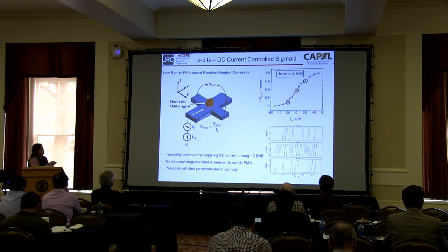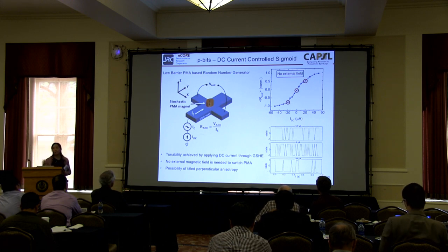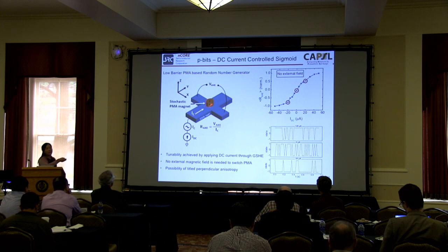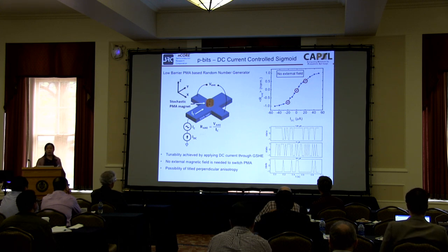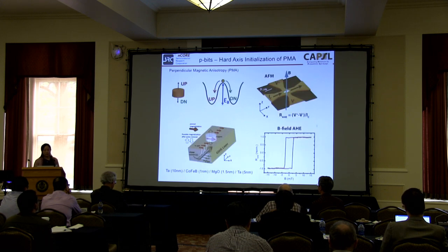And then now let's come to the device. I would like to really control this input through electrical means. So now we actually have our whole bar made out of a giant spin Hall effect material that actually offers spin-orbit torque. So I can really impact the magnetization of my magnet through the GSHE layer. And so here we apply a DC current. And again, you see the sigmoid curve through the giant spin Hall effect, the SOT effect, that we were able to control the average magnetization, which is reflected by the anomalous Hall resistance here.